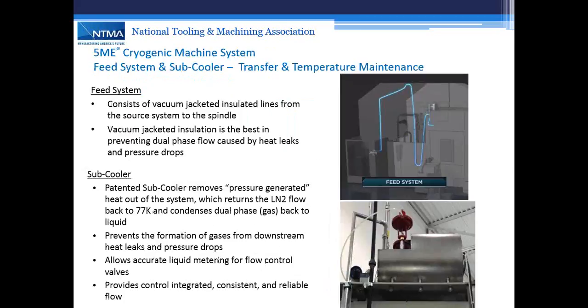The feed system, like almost all the components in the cryogenic system, is made out of stainless steel. Stainless steel is one of those materials that does not embrittle at cryogenic temperatures, so it's a very safe metal to use under these temperatures. And it's all vacuum jacketed. Flexible lines, rigid lines, the dewars, for example, even the subcooler has an inner vessel or inner tube in the lines, surrounded by an external stainless steel tube, and then we extract a vacuum between the 2 tubes with nothing between them. There is nothing for the cold energy to propagate to the outside. So inside the tubing, you'll have minus 321 degree liquid nitrogen. The outside, you can actually hold on to at ambient room temperatures.